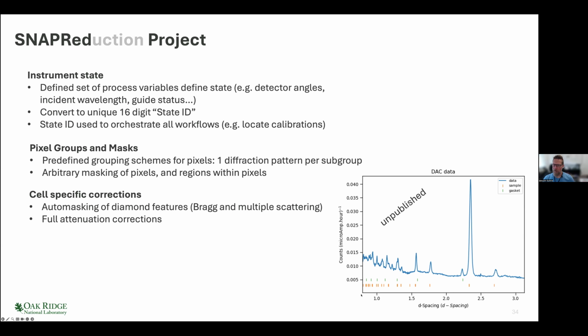You can see on the scale here, this is 0 counts. So this is true signal to background. And every peak here, apart from this one, which is coming from the gasket, is from the sample. And this is a hydrogen-bearing material. These are fully quantitatively analyzable data sets, which is something which previously would have taken weeks, maybe months to achieve. And now it's coming within minutes of starting the beam time. Yeah, and this has been running since the beginning of 2025, so it seems to be working really nicely.